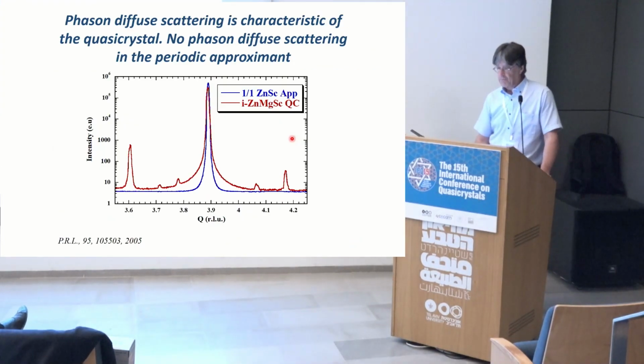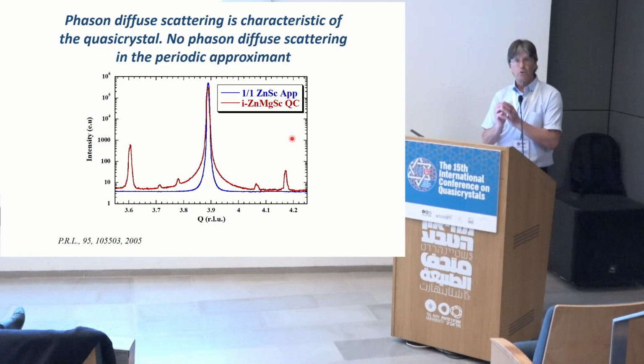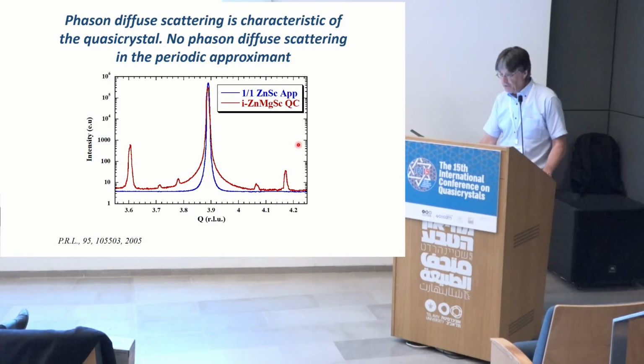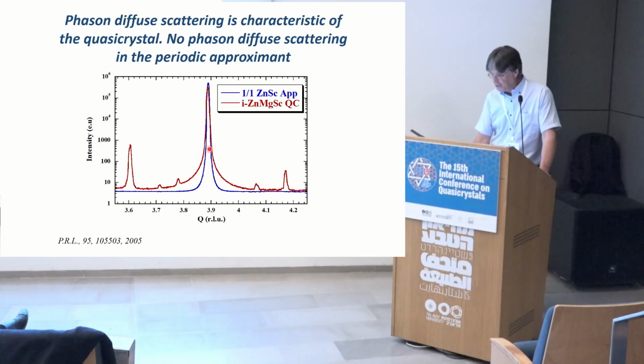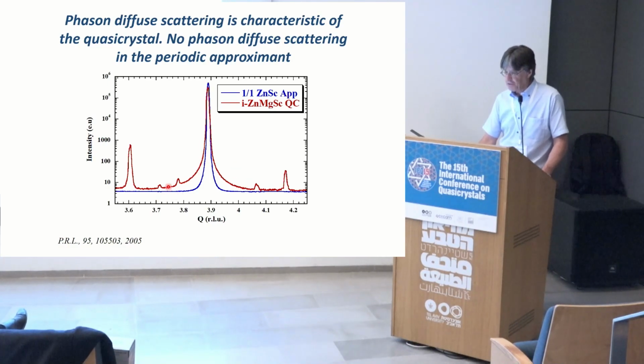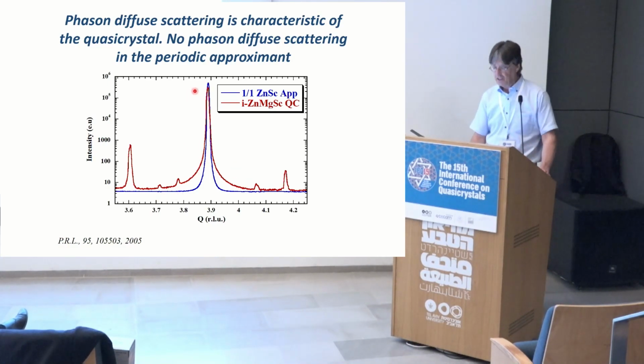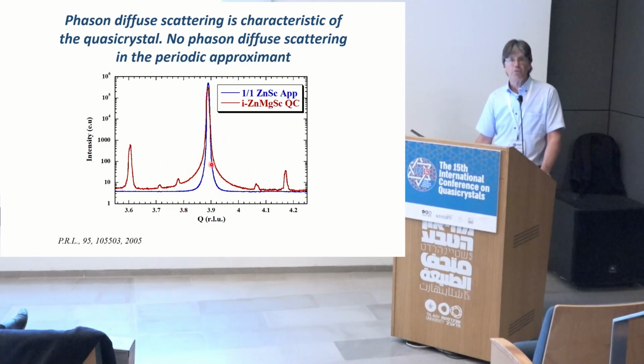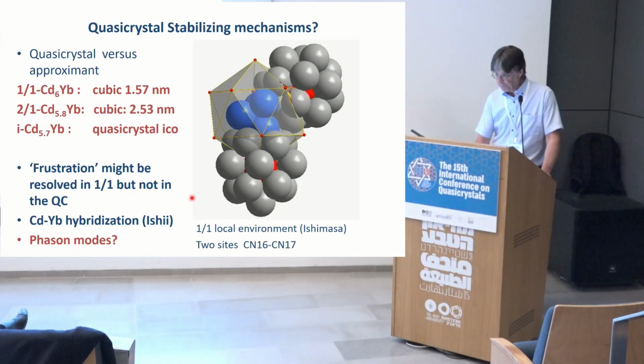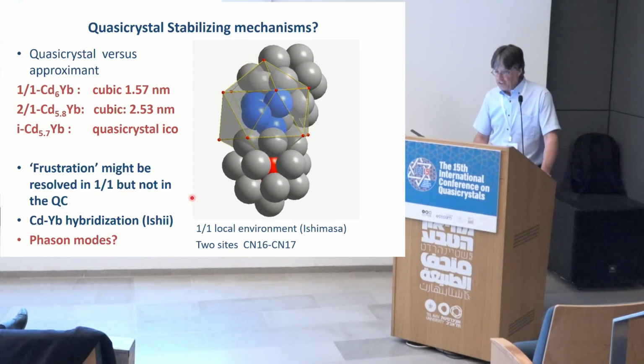And again, if we compare with the cubic approximant, there is a clear distinction. The blue line is the 1-1 approximant. The red line is the quasicrystal for the same similar Bragg peak. And you clearly see that there is an excess of diffuse scattering here, telling you that what is observed is due to the long-range quasi-periodic order.